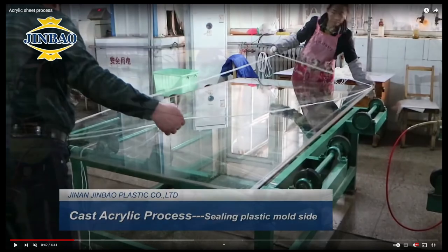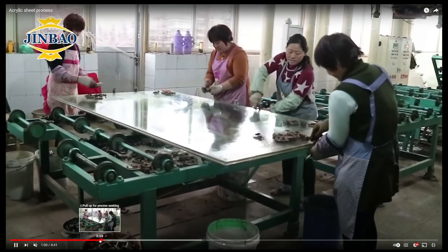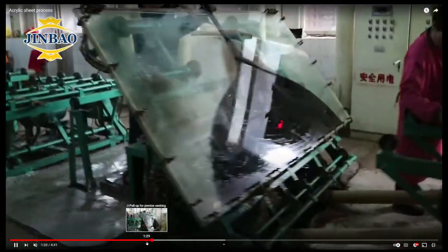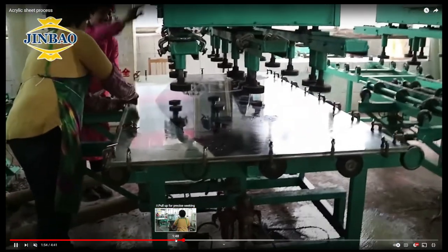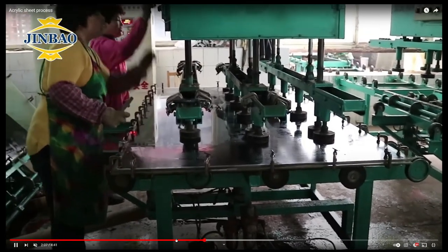Well, one major way is tolerance. Now, look, I think before we go any further, you think there's only two methods cast and extruded. I'm going to confuse the situation a little bit by explaining something else to you. Let's look at the way that they manufacture cast acrylic. Basically, they start off with a sheet of plate glass and they put some silicon tape around the edge. The thickness of that silicon tape represents the thickness of the sheet that they're going to finish up with. They then just blow the debris off the surface of the glass and they put another sheet of glass on top. Then in a very highly technical way, they clamp the glass sheets together. They then put an insert in the side of the sheet and then pour hot molten acrylic in between the sheets.